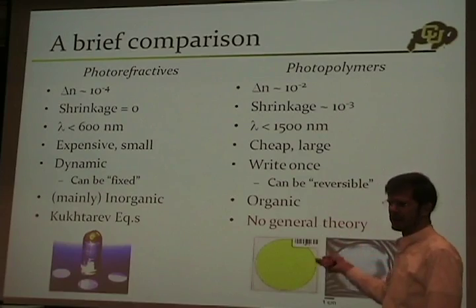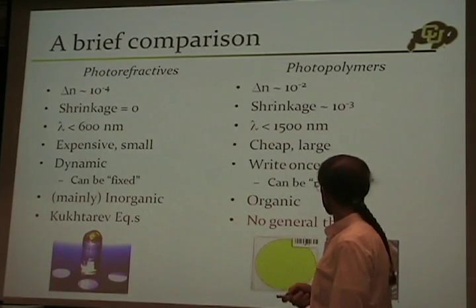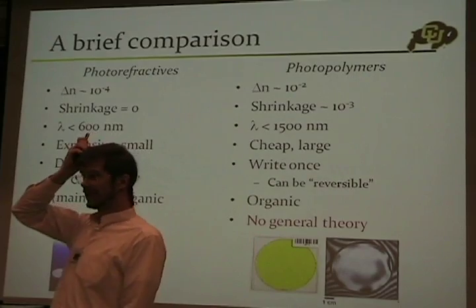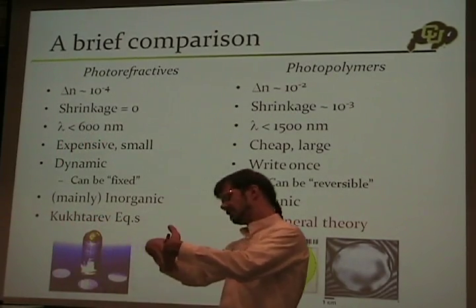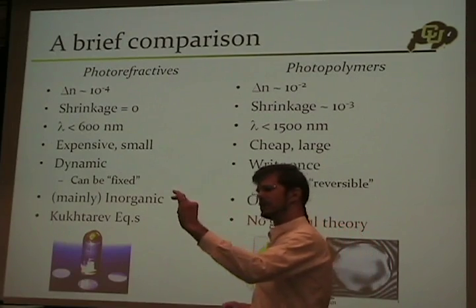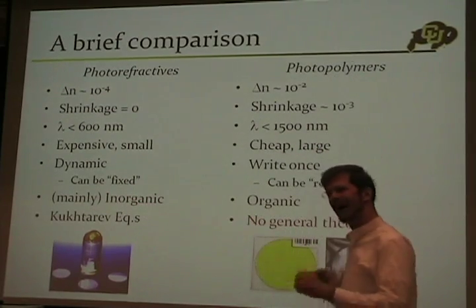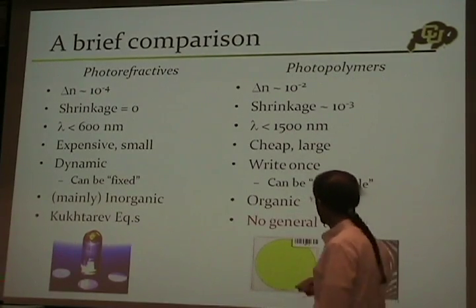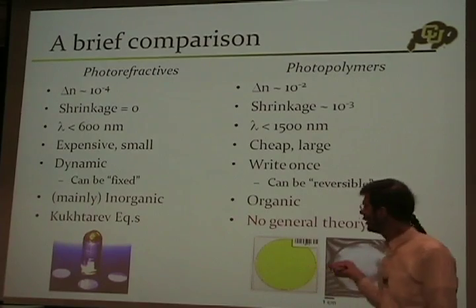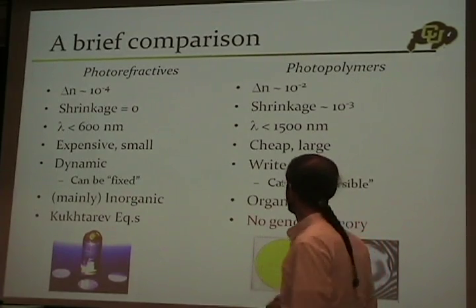Response time depends, because even here there's a dramatic range depending on the kind of material, intensity, and whether you put an electric field across it to cause drift instead of diffusion. Fick's law tells us that diffusion timescales are related to spatial scale squared. So if you're making holographic fringes with a 200-nanometer period, you probably have sub-microsecond response times. But if you expose an area a centimeter in size, it might be four days before the diffusion happens — so that's a broad time scale.